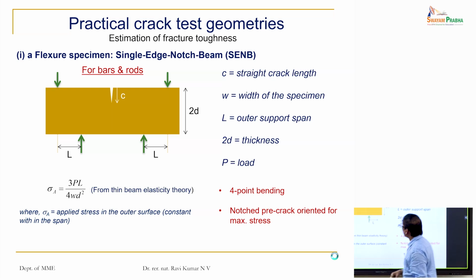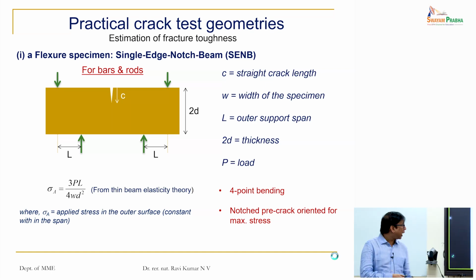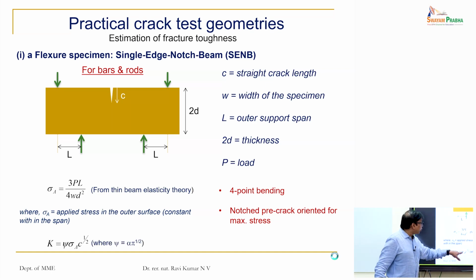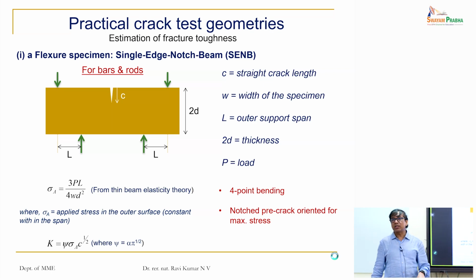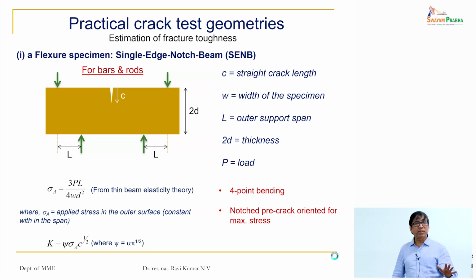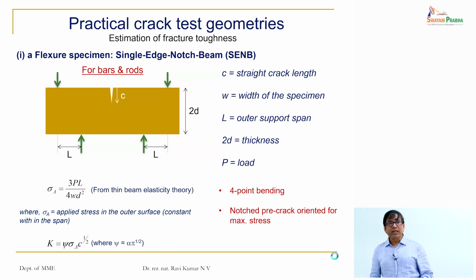And once you know the critical failure stress, you can actually calculate K, because you know the critical stress, you know the critical crack length, you can calculate the fracture toughness. So this is something that you have to do; it's an acceptable ASTM standard method, single edge notch beam, and you can do this. That will give you a measure of the fracture toughness of the material.